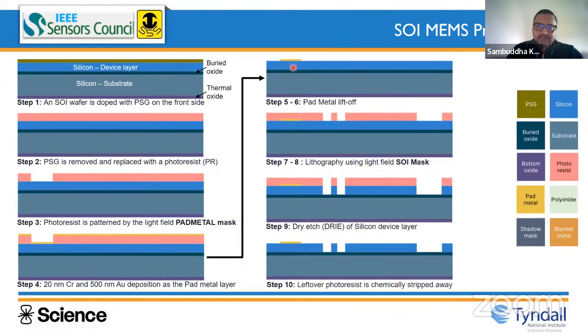So here you see after the lift-off process is done, the pad metal is deposited wherever you want the pad metal to be. Then we go for the most important mask, what we call the SOI mask, which defines the actual device that you are going to fabricate. So we go for another lithography step with the photoresist, pattern the photoresist with the mask, and then we go for the etching. This etching etches the silicon by 25 micron, using a process called deep reactive ion etching.